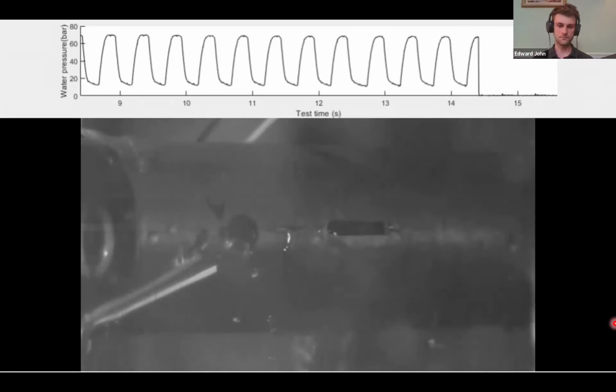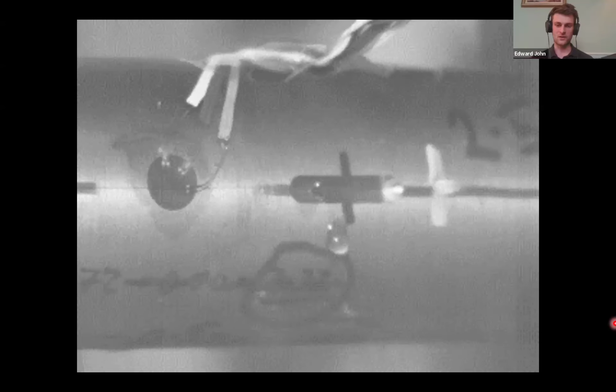So this next video shows the same arrangement, but the pressure is about 75% lower, or at least the amplitude of the pressure is 75% lower than the previous test. And instead of that very vigorous water jet, it's basically the same process, but the initial crack is much smaller. We're just getting a kind of dribble of water coming out.